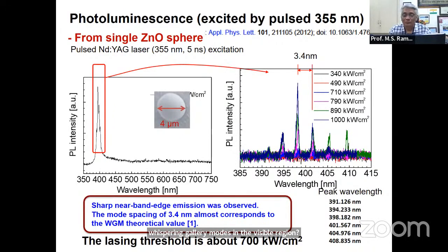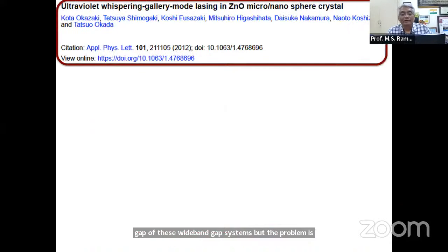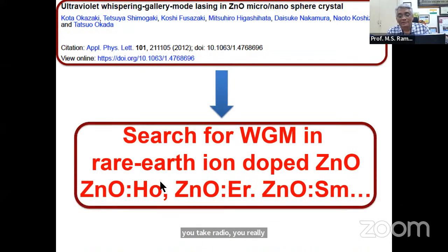So we decided to dope zinc oxide, not with transition metal ions, but with rare earth ions. Rare earth ions always create multiple electronic levels in the forbidden band gap of these wide band gap systems. But the problem is you really cannot dope large concentrations of holmium, erbium, or samarium, because of size mismatch - the ionic radius of zinc is 0.72 angstroms versus 1.018 angstroms for holmium. So the solid solubility limit is very low.